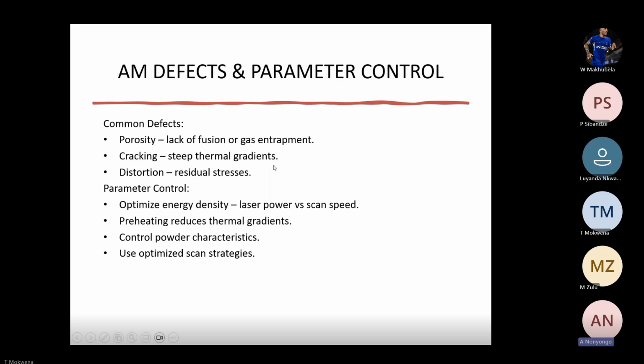I will also take you through additive manufacturing defects and parameter control, which are preventative techniques. Additive manufacturing experiences defects such as porosity, cracking, and distortion. Porosity occurs from insufficient melting, unstable melt pools, or trapped gases, which weakens fatigue resistance. Cracking is caused by steep thermal gradients, typically in titanium alloy printing, while distortion results from residual stress accumulation during rapid melting and cooling.